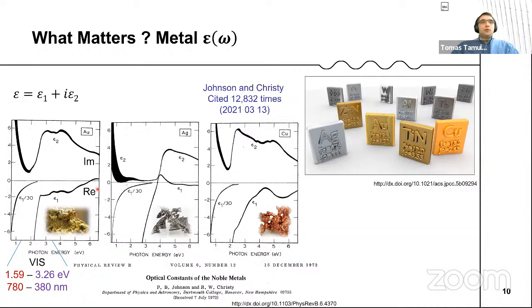those two authors announced what are the dielectric constants of gold, silver, and copper. On the top we have the imaginary part, and at the bottom the real part of the dielectric constants. Actually, this part of energy could be addressed to the visible part of the spectrum. And we have some transitions here that are called the interband transitions, and therefore gold has a yellowish color, and copper looks reddish, while silver has this metallic look because its interband transition is not in the visible spectrum. So the dielectric constant, the real and imaginary part are written like that, and the overall is this complex dielectric function that is important for us.